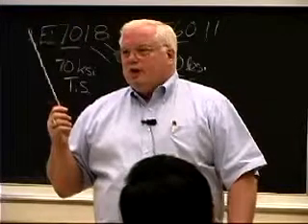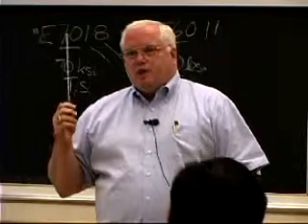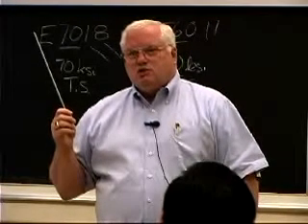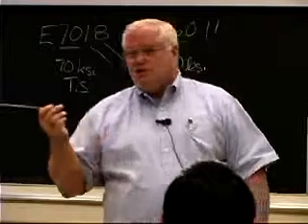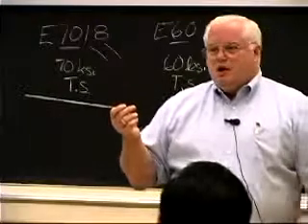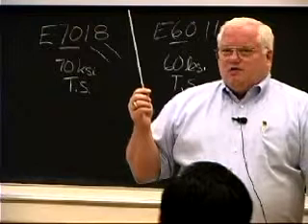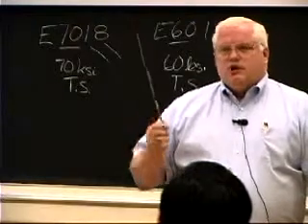Typically, you analyze these for their water content, and you want to be less than 0.2% by weight of moisture, which is pretty low, which usually means you stick these in an oven at like 300 or 400 degrees. If you go to the shipyard, they typically will only allow these out of the oven for about 4 hours. Different specs for different steels.